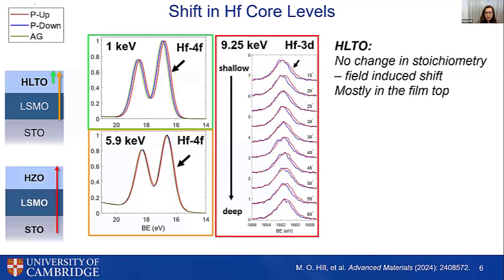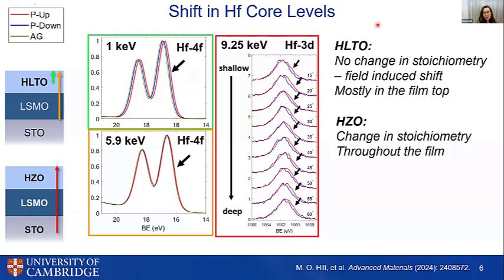Then looking again at HZO, we also see some effect in the P up condition in the hafnia 3d spectra. And in this case, what's different is that this isn't just a shift, it's actually a broadening of our peak. This suggests that we're getting a change in stoichiometry, specifically a reduction in hafnia in the P up condition. And we see this throughout our film, regardless of depth, suggesting it's not just happening in the top surface.